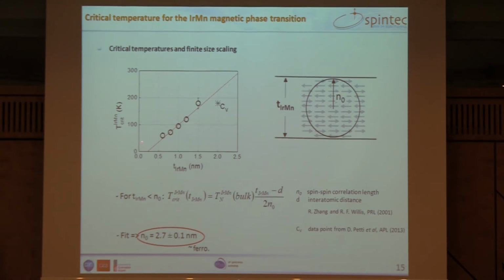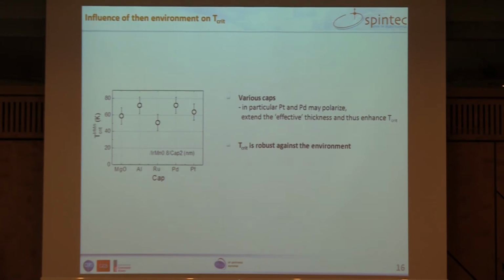Our data also agree pretty well with what can be found in the literature to date, which is one data point. This is this one. It's a data point that was measured by another group by calorimetry. Yes, this is the evolution of the critical temperature as a function of the different caps that we are putting. Actually, here we wanted to test two things. We wanted to see if the Néel temperature, or the critical temperature, is robust against its environment. We thought that maybe if we add platinum or palladium that can get polarized, we could somehow gain one extra polarized layer, and we could this way increase the Néel temperature. But it didn't work out very well. But the good conclusion is that the critical temperature seems to be robust against its environment.